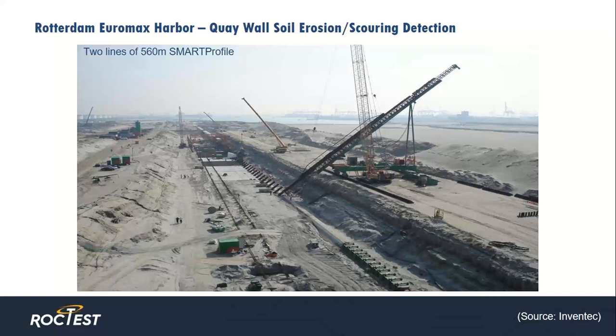Of concern in this particular installation is the degradation of the backfill material behind the two quay walls that are going in on either side of this. Two lines of smart profile cable were embedded in the backfill material behind the quay walls to detect and localize soil degradation zones over the length of the pier by detecting strain changes.